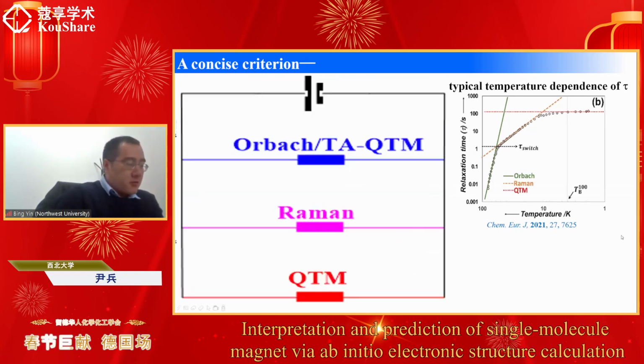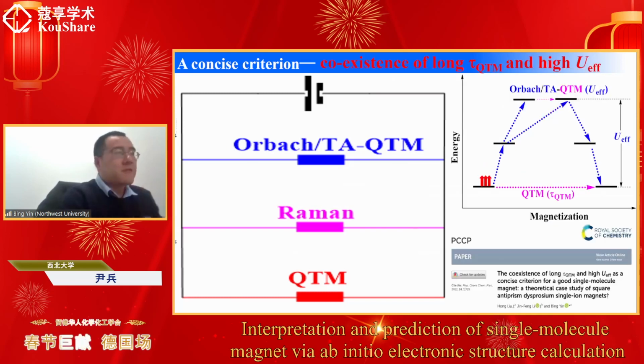The quantum tunneling of magnetization (QTM) in the ground state, and the Raman, as well as the thermally activated one, which is usually termed as Orbach or TQTM process. Furthermore, we could simplify the problem so that we only need to consider 2 pathways. One is QTM, the other is the thermally activated one. The QTM is characterized by the so-called QTM time, tau QTM, and the thermally activated relaxation is characterized by the energy barrier Ueff.